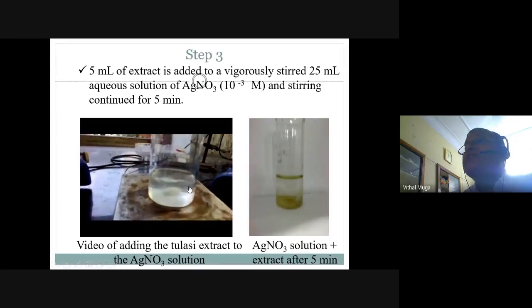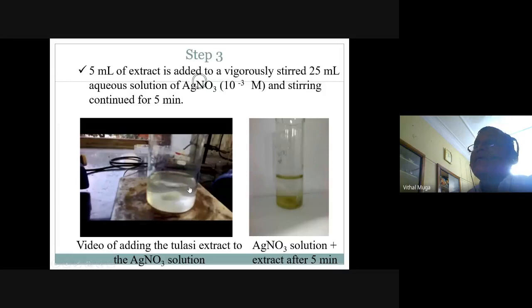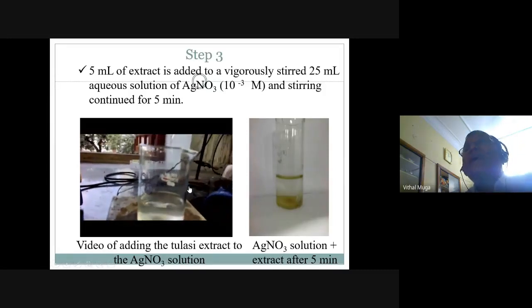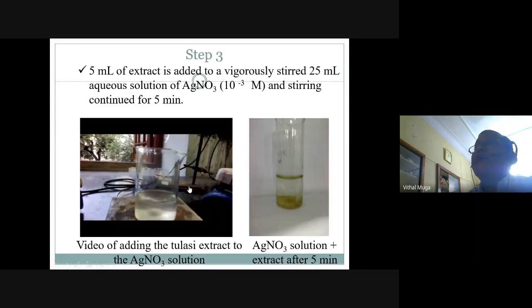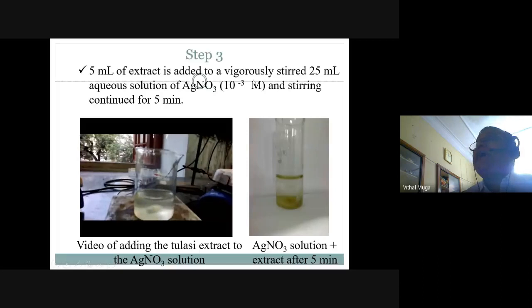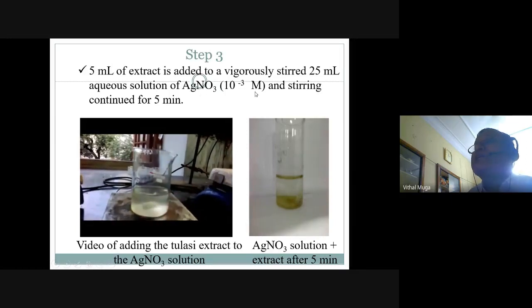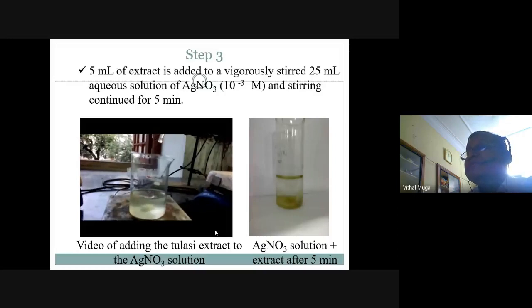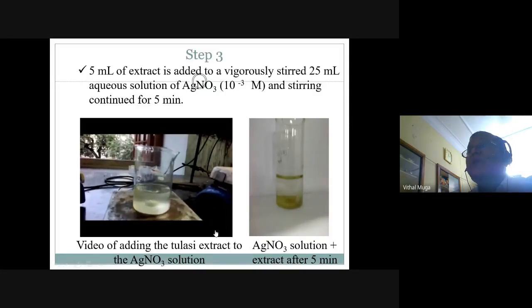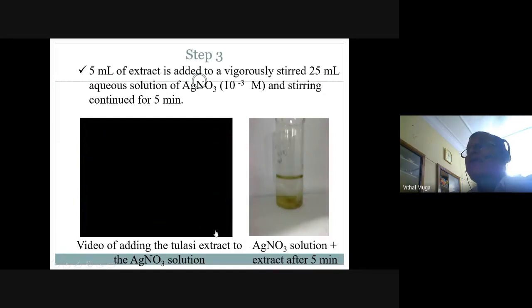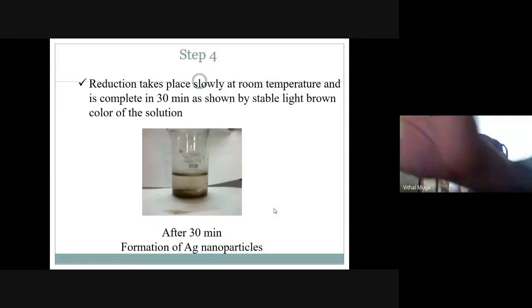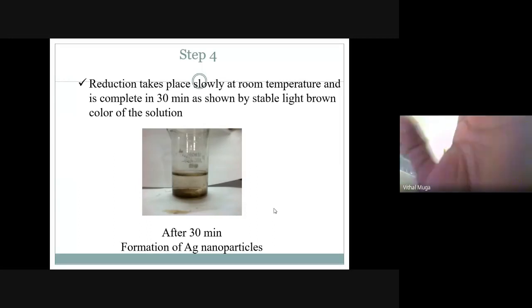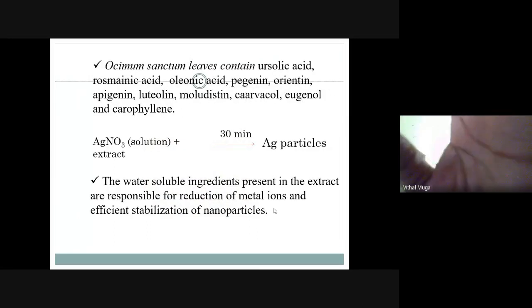The only thing is that I cannot show you the particles because that requires SEM or TEM. But you can record its UV visible spectrum and confirm that silver nanoparticles are formed. So I have taken 5 ml of the extract and stirred it, and then 25 ml of aqueous solution of silver nitrate, and for 5 minutes you do it. After 5 minutes it looks like this. Immediately you may not be able to distinguish that silver nanoparticles are formed, but after 30 minutes you see the color has changed, and I will show you the spectrum also.